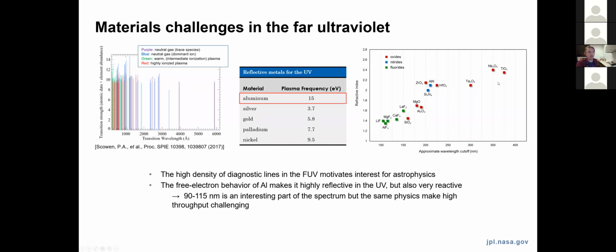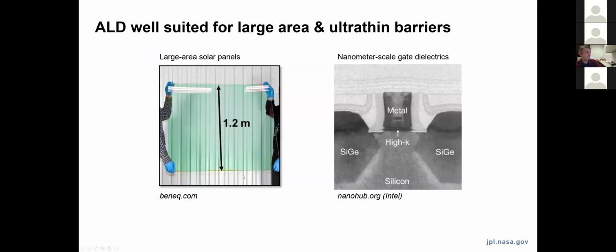So at longer wavelengths, you have a pretty wide selection of optical coating materials to choose from with a pretty broad range of refractive indices. So your job as an optical designer is relatively straightforward. But then as you move down into the far UV, you're left with really just a handful of metal fluoride materials that all have a relatively similar refractive index. And so you sort of run out of tricks to use in terms of the complexity of the coating, and you run out of materials to use essentially as an anti-reflective coating. So the same physics that makes this part of the spectrum interesting makes it really challenging from the material side.